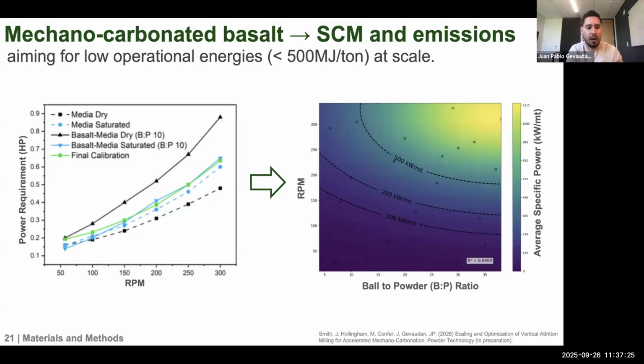We actually have another set of projects looking at creating a discrete element method model to create a digital twin, so that when we scale up that reactor technology, we can achieve this low operational energy. On the left here, you're seeing our reactor operating, with the x-axis at different RPMs and the power requirement on the y-axis. What we have done is calibrated that discrete element method model, our digital twin, with some of our experiments to make sure that when we scale it, which is on the right side, we can actually pick those operational parameters that lower the specific power, the kilowatts per metric ton. So more work on this later, and we'll be able to share some of this in preparation work. But it's really important that we consider how much energy we're actually using here to produce SCMs.